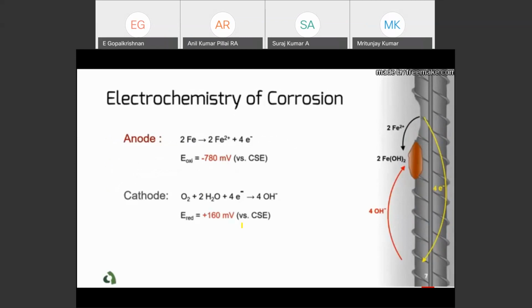Corrosion happens in this environment, and the movement of electrons in concrete creates an electrical potential field inside concrete over the surface of rebar. For example, the reactions in the anode, where steel loses electrons, can create a potential difference of negative 780 millivolts compared to a standard copper sulfate electrode. The cathodic reactions would result in a potential difference of positive 160 millivolts.